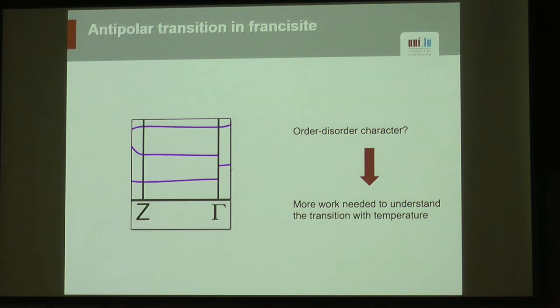But there is a bit more to it if you think of what you're trying to do here. Because what you're trying to do is to have an unstable phonon mode at gamma, and yet preserve something where the instability in reciprocal space is really limited to a narrow vicinity of the Z point. So if I wanted to sketch the phonon branch corresponding to that, I would have to do something like this, probably, or something a bit weird that doesn't look like something you find usually in this kind of phonon calculation. So this highlights to me the difficulty or the originality of this kind of transition, and just says that there is more fun going on with the system.